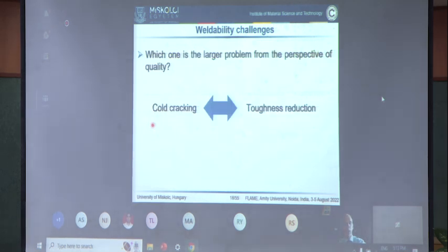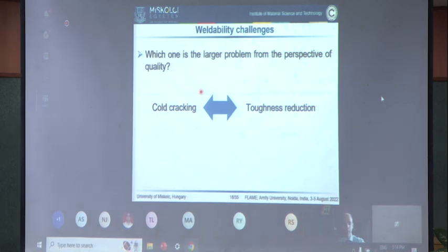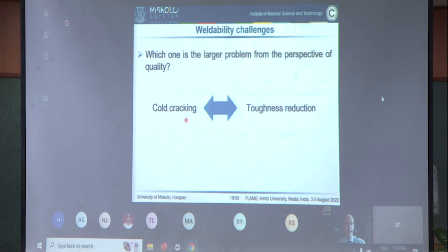The question arises, which one is the larger problem from the perspective of quality, the cold cracking or the toughness reduction? After consulting with many welding engineers, we concluded that the toughness reduction is a bigger problem, because if we consider the production route of welded structures, the structures are welded, and then before they are transported to the customers, there is always non-destructive testing, for example, ultrasonic testing, radiography, or simple visual testing, penetration testing. So the presence of cold cracking is always identified. Generally there is very low risk that we have a welded structure in the market with cold cracks. But for toughness, we do not have any information.